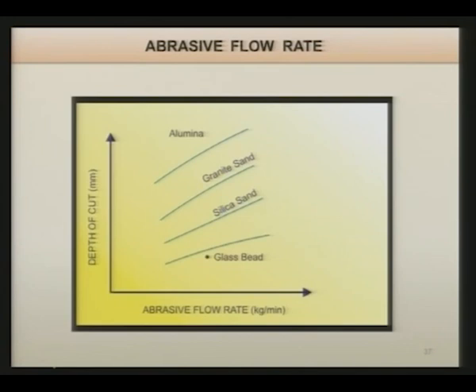Now, as we can see here, as the abrasive flow rate is increasing, the depth of cut is increasing for different kinds of abrasives: glass bead, silica sand, granite sand or alumina. One thing we can see here is that, depending upon the type of the abrasive, the depth of cut is different in different cases.